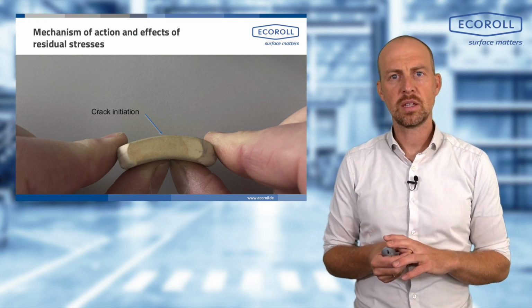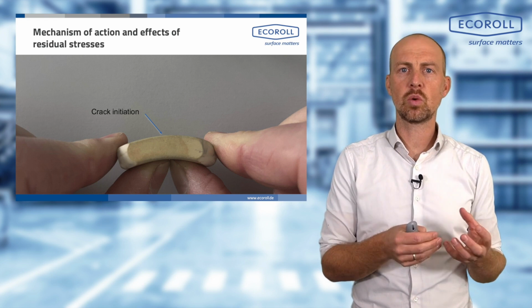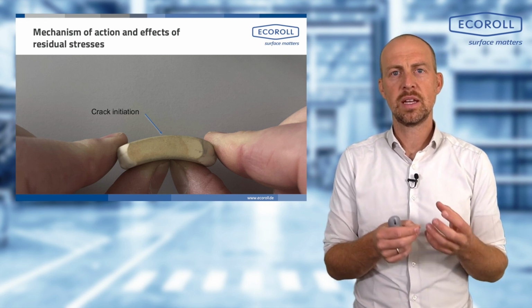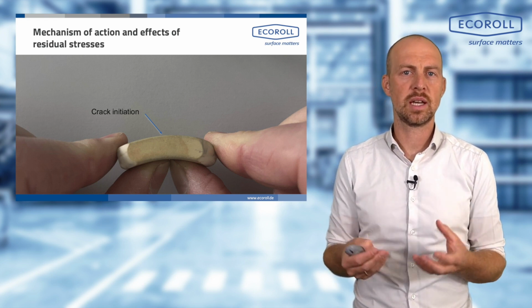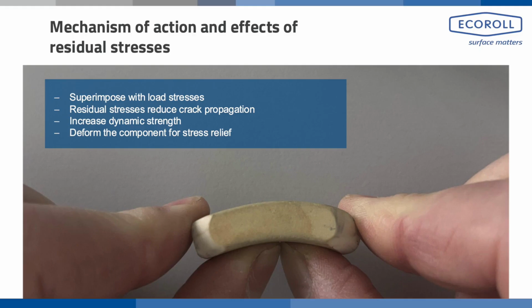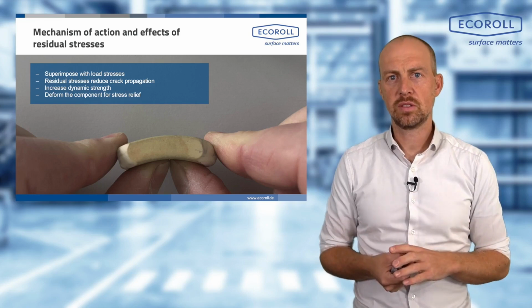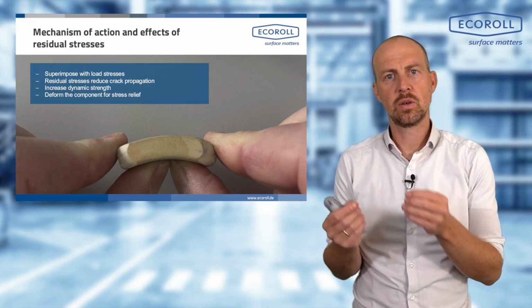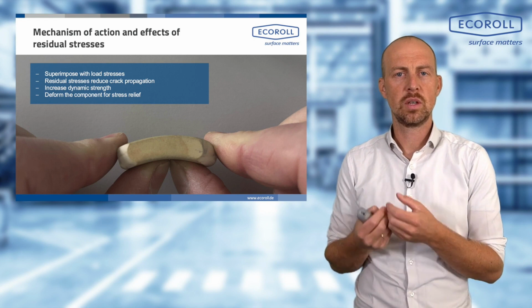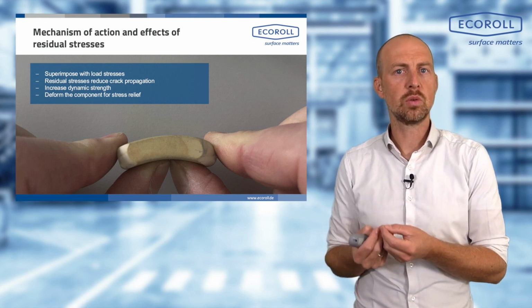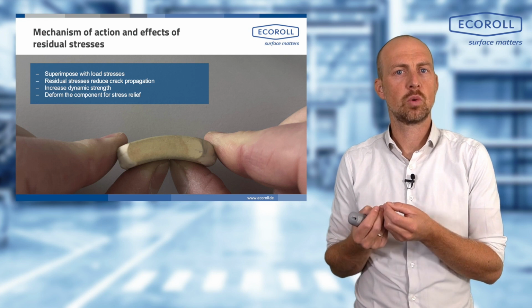We want to ensure that compressive stresses are present or contained in the component, which then essentially counteract crack propagation and crack initiation. That means residual stresses overlap with the applied stresses. My compressive stress, so what I just did with the eraser compressing it, simulates my compressive residual stress, and these overlap with the load stress from the bending. So compressive residual stresses have a positive effect on crack formation. They help ensure that cracks form later, and they also slow down the propagation of cracks once they have formed.